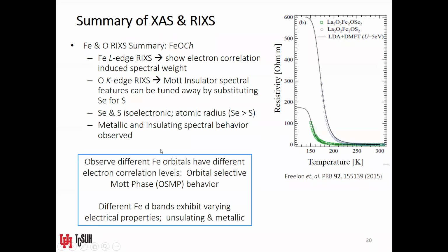So what we see between the iron RIXS and the oxygen RIXS is insulating behavior shown by the iron RIXS clearly, where both Mott insulators have this correlation-induced high energy spectral weight. However, the oxygen RIXS shows a mixture, that one of the materials is less insulating than the other. So we have both metallic and insulating spectral behavior observed here. All of that is consistent with this idea that there is some orbital selectivity to the Mott insulating nature of these materials, as people have observed across numerous iron-based superconductors as well.